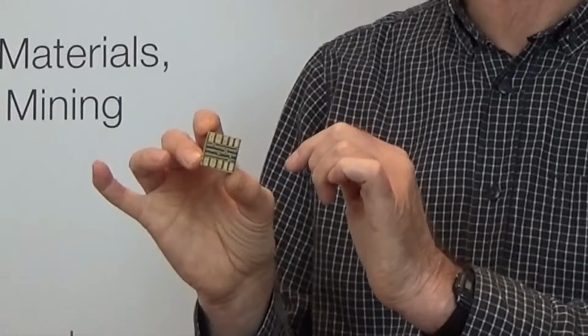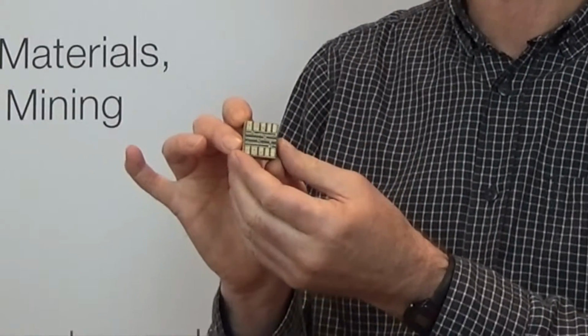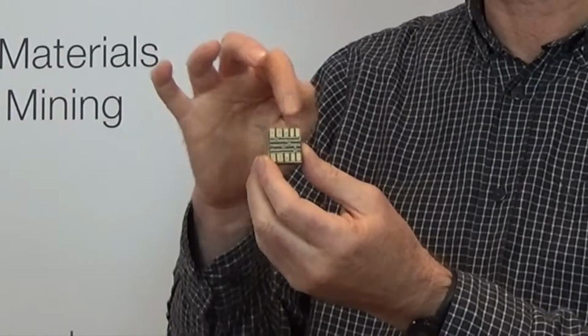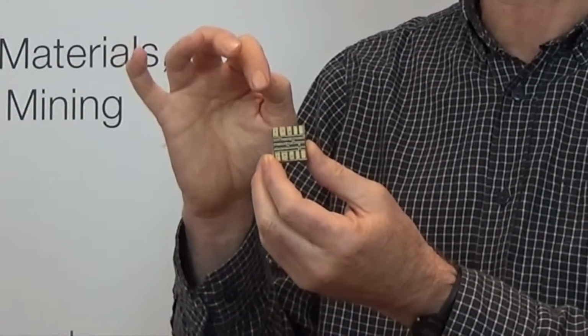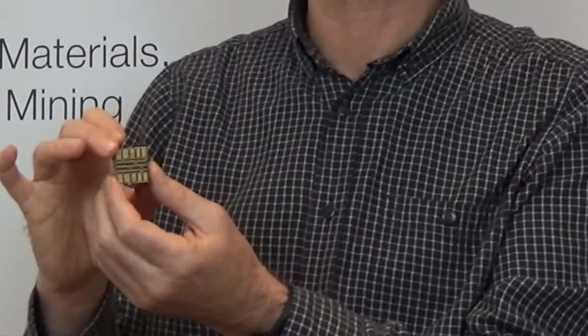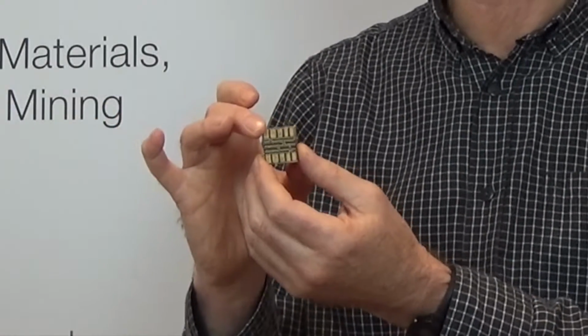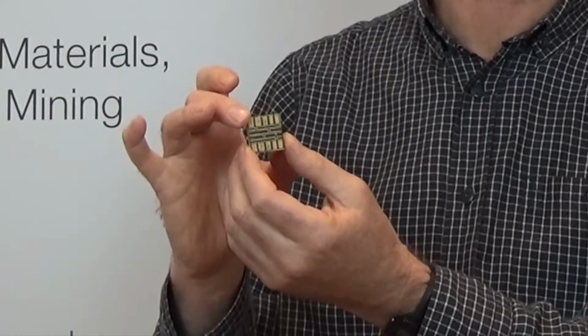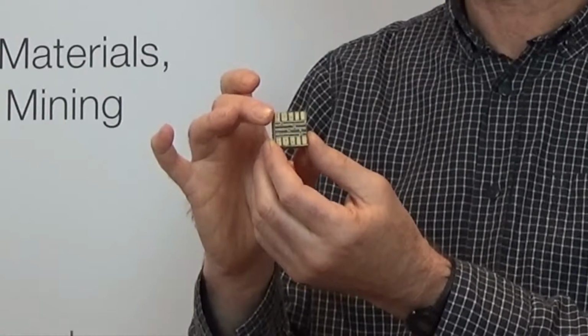Because it's a hollow structure, and these very stiff cellulose molecules are oriented around the cell wall in a spiral, wood ends up with an elastic modulus of about 10 gigapascals, so a reduction of a factor of about 14. So in making wood composites, we're trying to make the very best use of a structure which is already a composite material, and what we're aiming to do is to improve properties in all directions in engineered wood products.